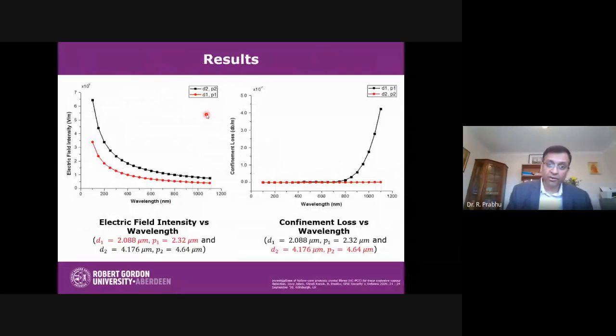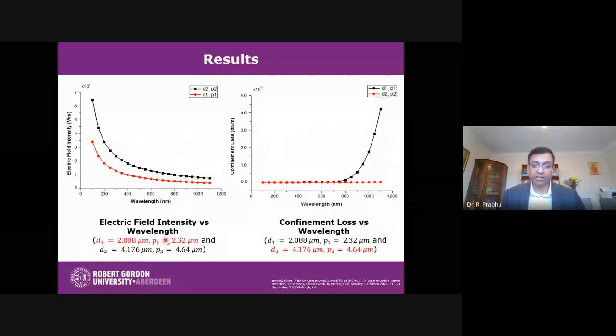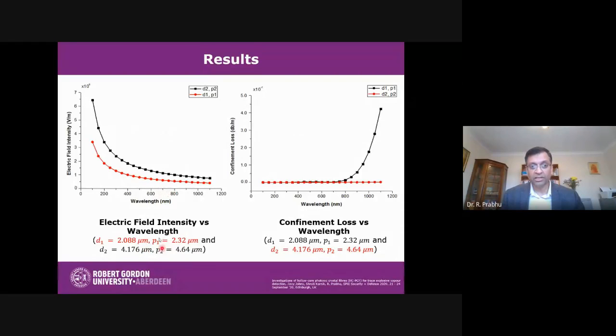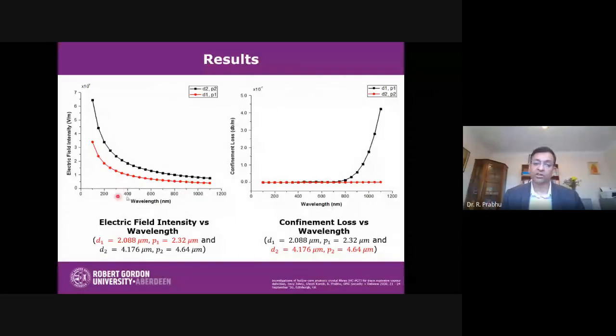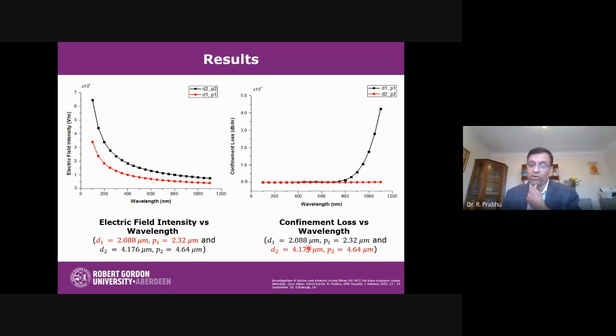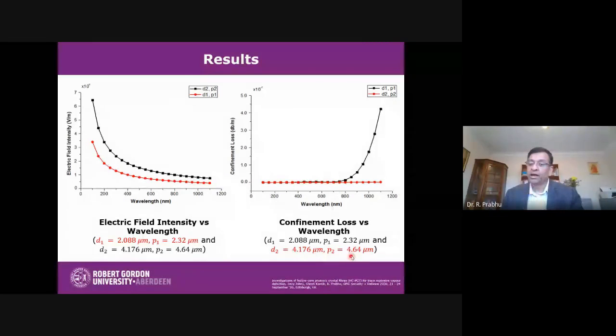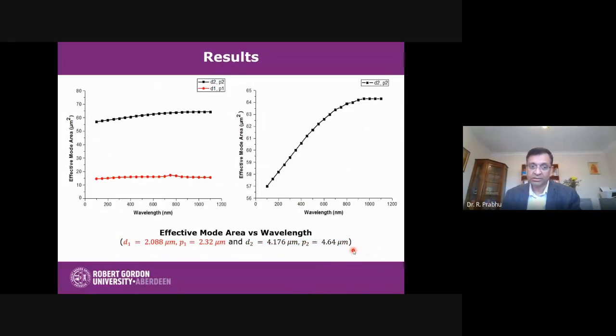One of my PhD students was trying to model this behavior, and she was trying to vary the pitch and diameter of the holes. She found that as we increase the diameter of the holes and pitch, the electric field intensity is increasing as a function of wavelength. Again, the confinement loss is better if we go for larger pitch and diameter. I'll go slightly faster now.